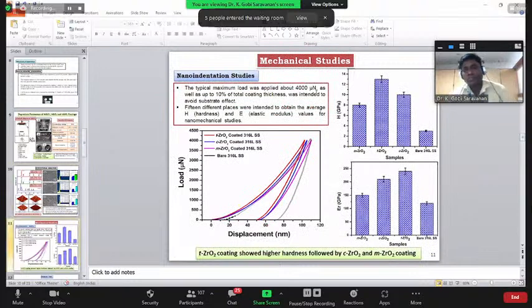From this we studied the mechanical properties using nano indentation. We applied a force of 4000 micronewton, which is 10% of the total thickness, in order to avoid the substrate effect. From this study we conclude that the tetragonal zirconia shows higher mechanical strength than the monoclinic as well as cubic. Because of this, tetragonal zirconia shows more fracture toughness than the monoclinic as well as cubic.